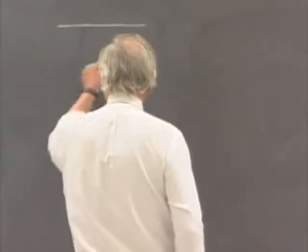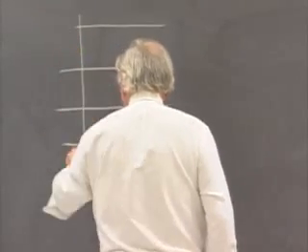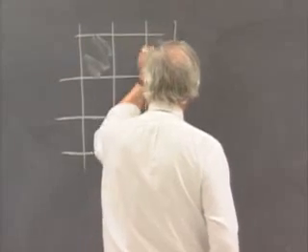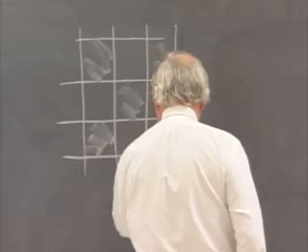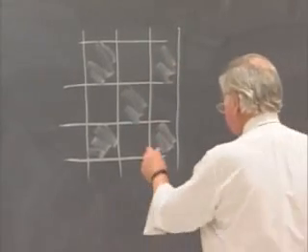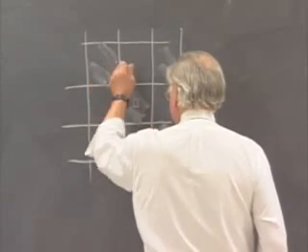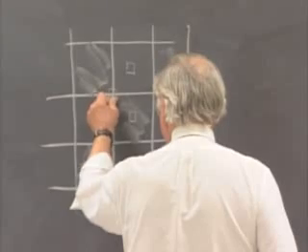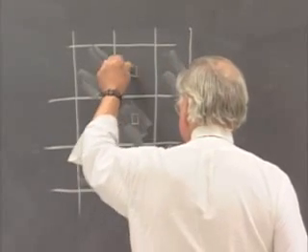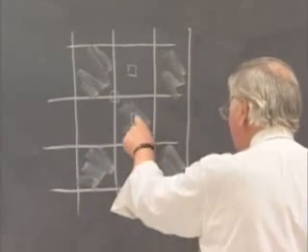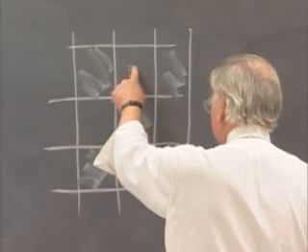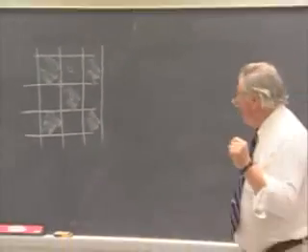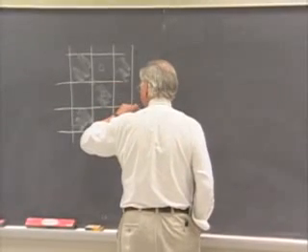And I would observe that this is something that you are already very familiar with in patterns. In particular, in the pattern that is represented by a checkerboard. Okay, where you have black squares and white squares. This location here is a bona fide 4-fold axis, as is this location here. But there are other locations, such as the corners of the black and white squares, where indeed there is a 90-degree rotation that takes this square and transforms it into this square. But in doing that transformation, you change it from a black one to a white one, and then from a white one to a black one again, back to a white one. And that is a color symmetry. You could make it red and green if you like to be a little more attractive.